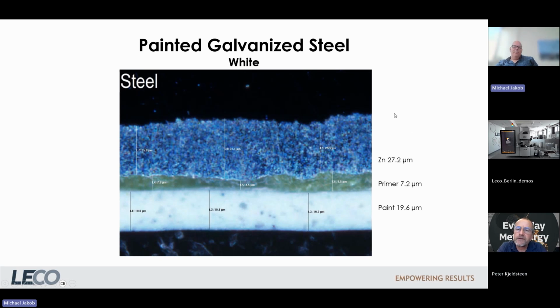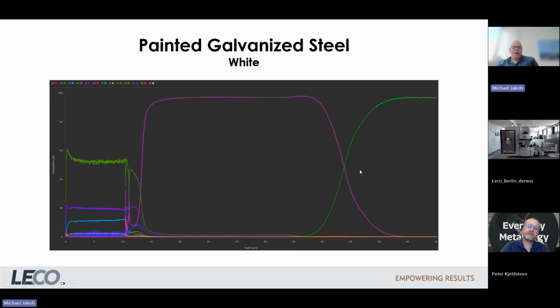This is a white car. And you see that's the surface. That's a cross section by metallography. Then you see your steel, you see your paint, and you see some zinc layer and some interlayer. And what you finally get is something like this. You see, at the beginning, from the surface, some oxygen, some titanium, of course, and some carbon of the paint, which I wouldn't call plastic, but anyhow, it has carbon. But you see titanium oxide, the white color. Then you have your zinc layer, and then after 50 or 60 microns, it's difficult to see here from my screen, you go into the steel. That is something you can do.